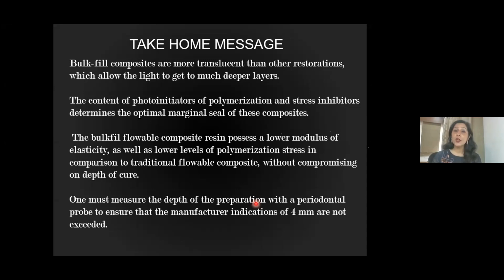The content of photoinitiators of polymerization determines the optimal marginal seal of these composites. So my dear friends, what I want to emphasize is that if your initiators have been activated by the light cure, when you are using it properly, then there is a lot of free radical generation, and this free radical takes care of the complete polymerization, and so gives a good marginal seal as well. The bulk fill flowable composite resins possess a lower modulus of elasticity as well as lower levels of polymerization stress in comparison to traditional flowable composites. This is what I wanted to emphasize: traditional flowable composites give a lot of polymerization stress to the tooth, whereas the bulk fills have much lower levels of polymerization stress without compromising on depth of cure.